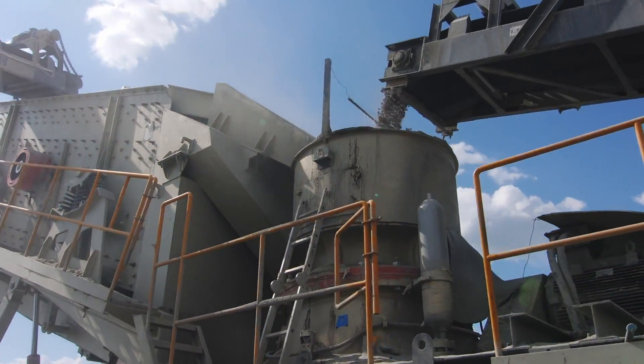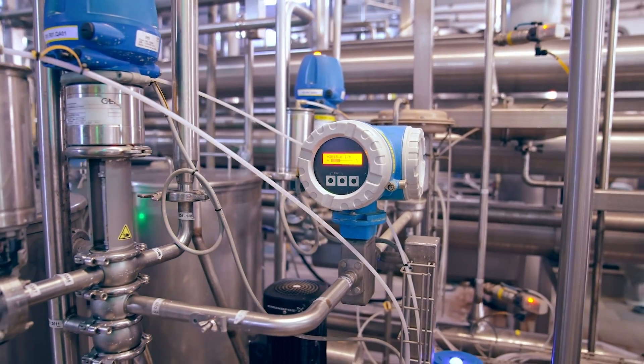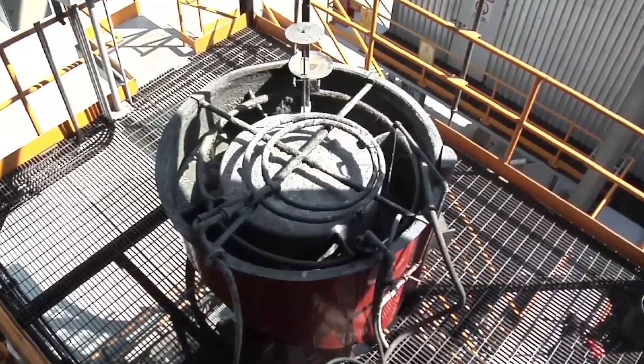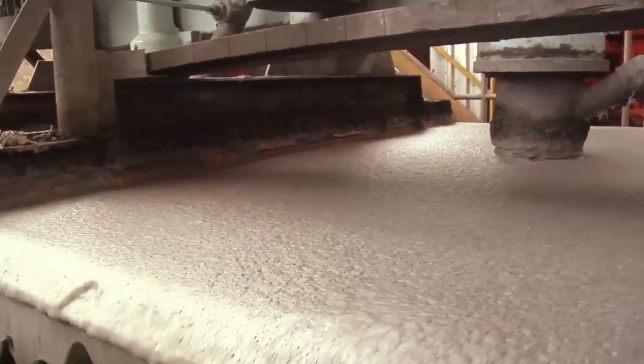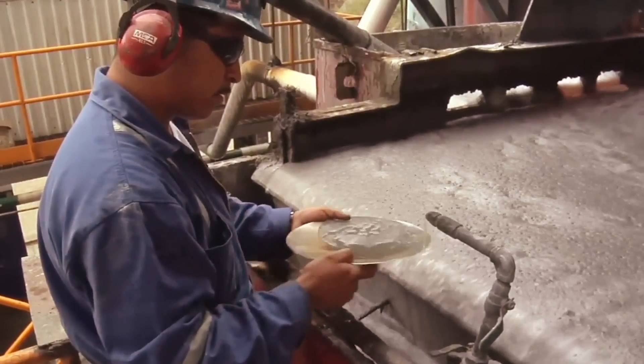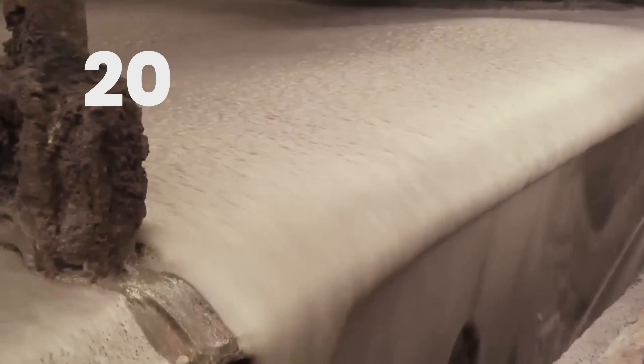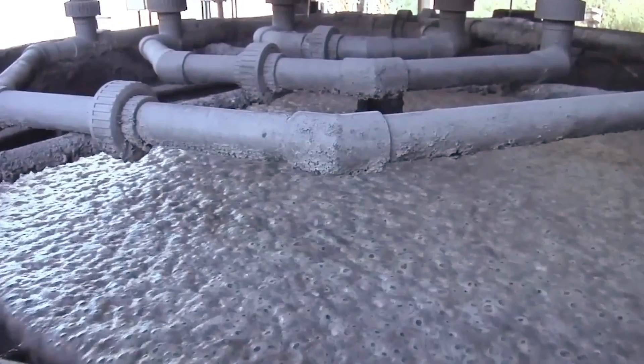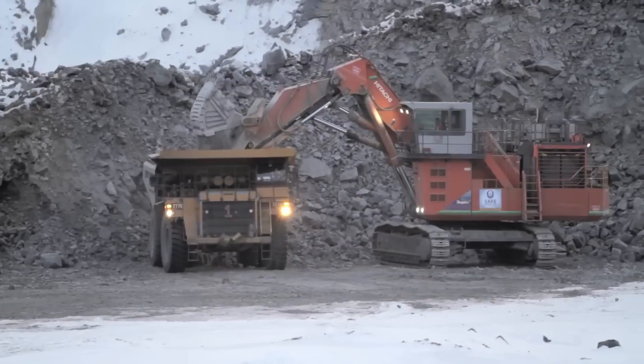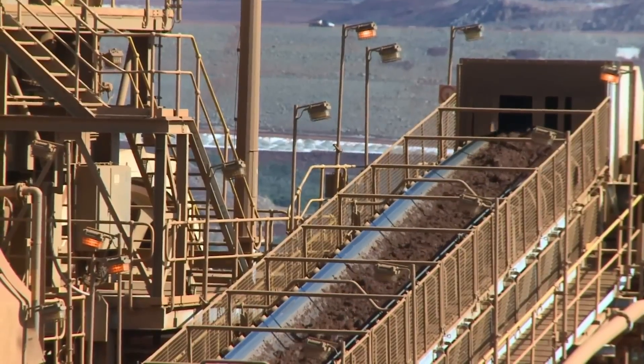This exponentially exposes more silver minerals for downstream separation while avoiding excessive overgrinding that could impair later concentration steps. The ground silver then enters specialized froth-flotation tanks filled with water, air, and chemical reagents. As compressed air bubbles up and agitates this pulp, the silver mineral grains preferentially adhere to the air-water interfaces based on the physics of hydrophobicity and surface chemistry. Skimmers collect this silver-laden froth as it floats to the top of the tank, directed into launders as the bubbles burst. The enriched concentrate now contains 20–40% silver by weight. Additional gravity concentration methods like jigs and spiral separators may supplement flotation, exploiting density differences to further enrich silver. Together, these processes transform the powdered ore into a concentrated silver product transported onward for smelting and refining.